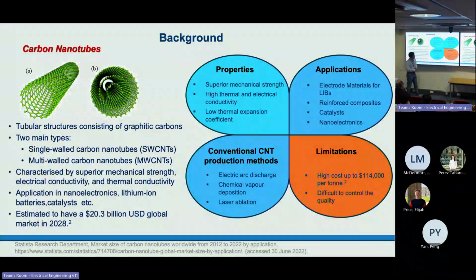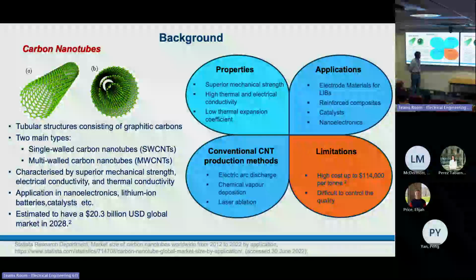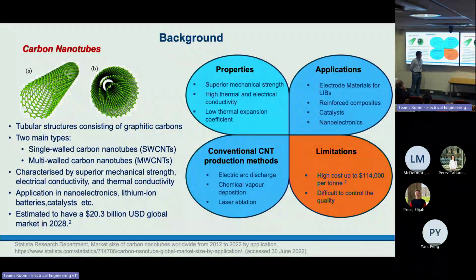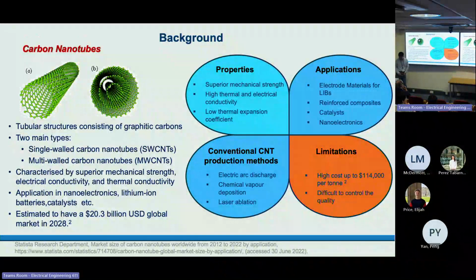There are mainly three conventional carbon nanotubes production methods nowadays. One is electric arc discharge, and also chemical vapor deposition and laser ablation. Chemical vapor deposition, CVD, is the most commonly used method to produce carbon nanotubes nowadays. But there are lots of problems facing carbon nanotubes application. One is the high cost, up to $114,000 per ton. And it's also difficult to control the quality, the size, and the structure of the carbon nanotubes using current methods.